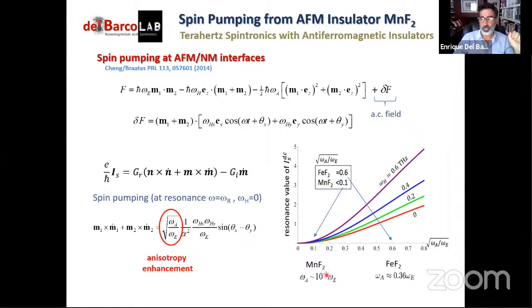For example, in manganese difluoride, the one that we have studied, the anisotropy energy is about three orders of magnitude smaller than the exchange interaction. And the spin current expected from that, at any field, is going to be much smaller than, for example, in iron difluoride, where the anisotropy energy is comparable to the exchange interaction. So one would like to work with iron difluoride. We didn't do this, not because we don't know what we do, right? It's just because the frequency of oscillation of this material is much larger and it's not accessible with our techniques. So we have to restrict our experiments to manganese difluoride for the moment.